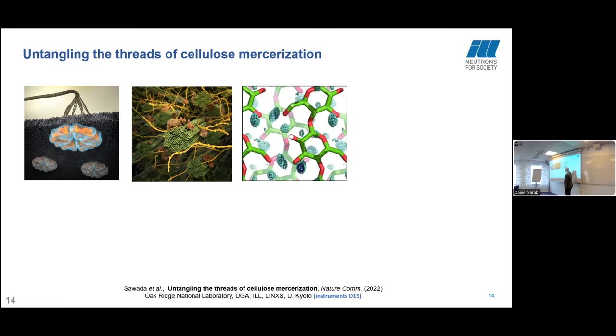And we also determined the crystal structure within each of the nanofibers, again using neutrons, because neutrons can see hydrogen, and these nanofibers or crystals are held together through hydrogen bonding. So hydrogen is the key. And this is a cellulose chain. You can see it's got a directionality. This end is different from this end because here there's a ring oxygen, here there's a hydroxyl group. Here's a hydrogen atom forming an interchain hydrogen bond. Here's a hydrogen atom forming an interchain hydrogen bond. But the key thing is that all the chains are pointing in the same direction.